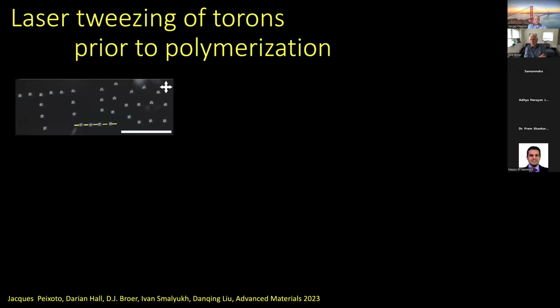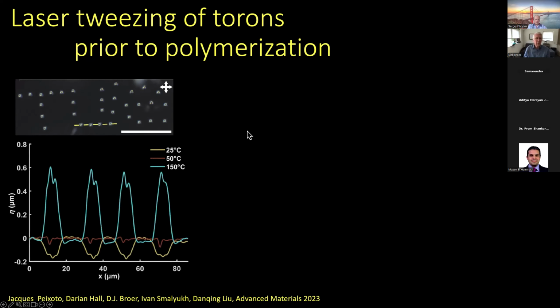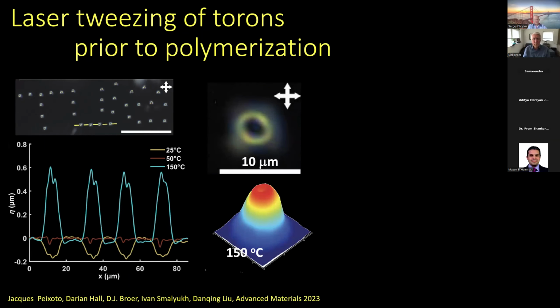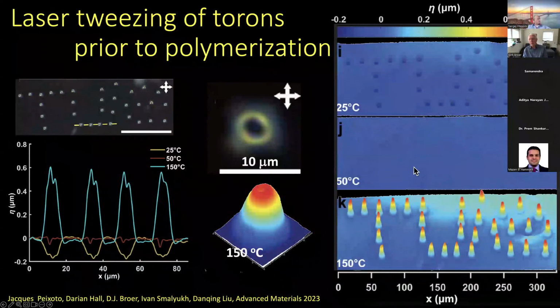And working with these torons, using the expertise of Ivan, basically what we can also do in the monomeric state when we have the torons, we can just pick them up by a laser tweezer, and you can place them at positions where you actually want to have them. In this case, we created our TU/e logo. And again, you can actuate them. The planar areas go up in the heating state, but go down in the cooling state. And this is the cross section of the toron. So again, a volcano type of structure. And by placing at the right position, well, you can make our university logo more visible.